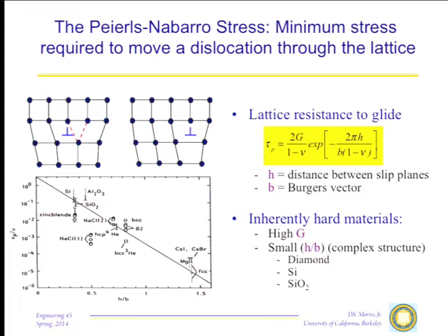I mentioned to you earlier that when I was recommending a material to use for a spring that would be predictable in its properties, even when the deformation was very small, I told them get rid of the body-centered cubic material, which is down here, and go instead to something like quartz, which is up here. Since these have such a high Peierls stress, it is very difficult to deform these materials at any low stress. As a consequence, these materials will truly remain elastic until you get a very high stress on them. Where these materials that have smaller theoretical strengths will accumulate internal stresses and tend to deform under relatively low stresses, at least a little bit. So if you want something that's really going to behave elastically, you want to be up in this region here, very high Peierls stress.